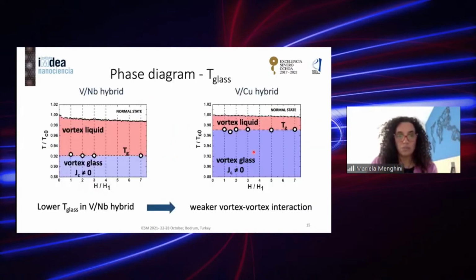So when we do this analysis for both hybrid systems, this now is the HT phase diagram. So we plot the temperature as a function of field. It's normalized in this case again by the matching field. So this is the HC2 line, of course. And then what we see is that for the vanadium niobium hybrid system, this glass transition temperature is much lower than in the case of the vanadium copper hybrid system. So this lowering of the glass transition temperature indicates that there is a weaker vortex-vortex interaction in